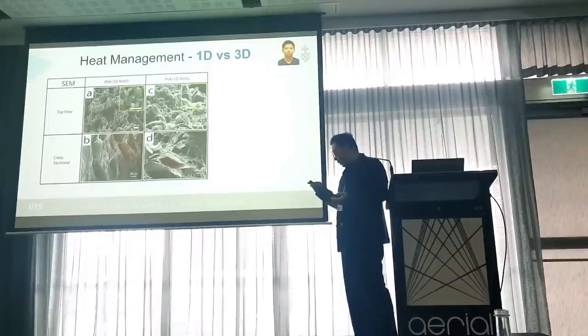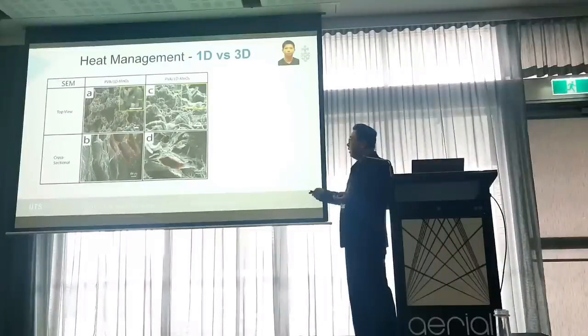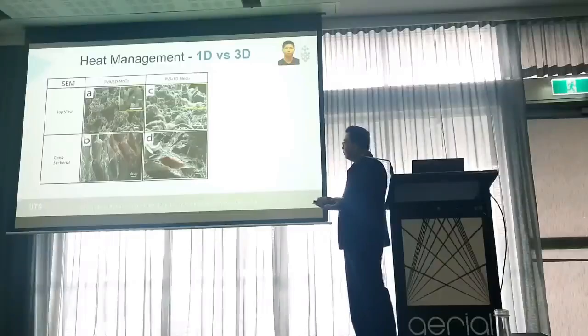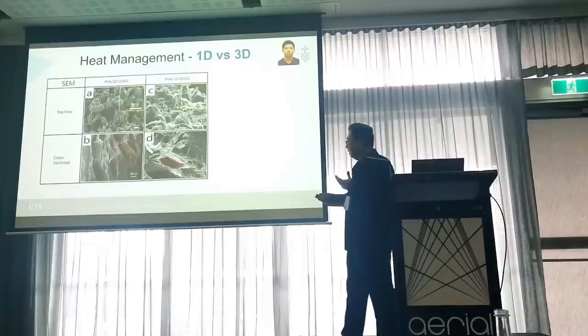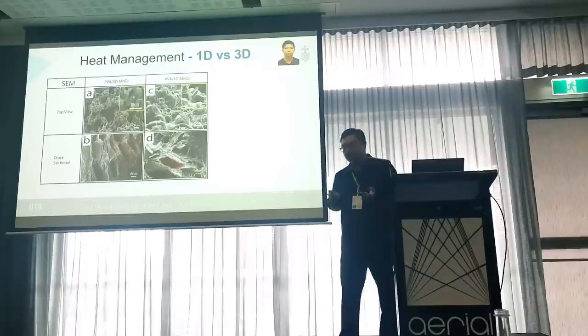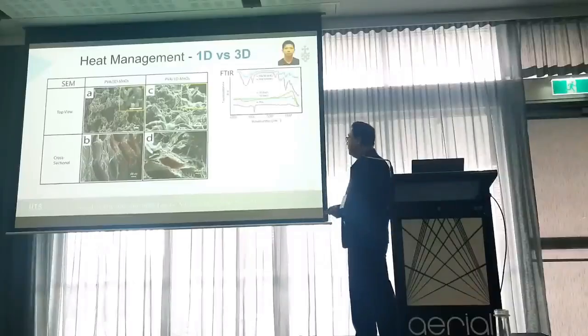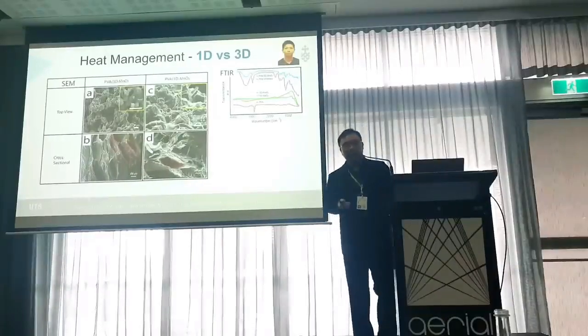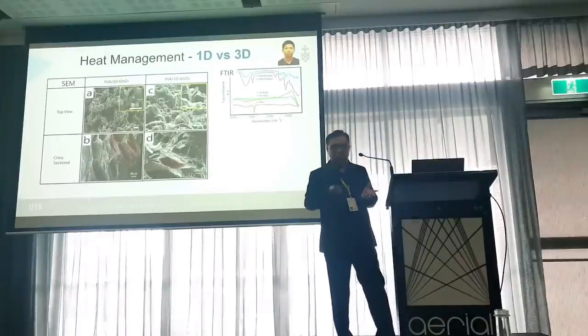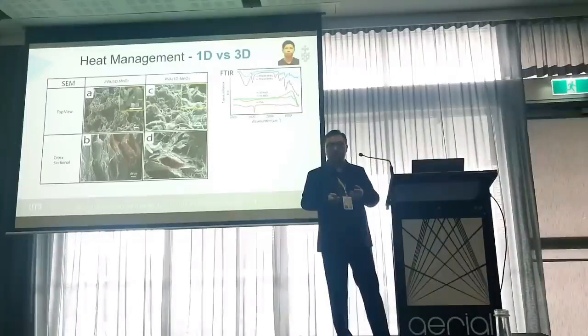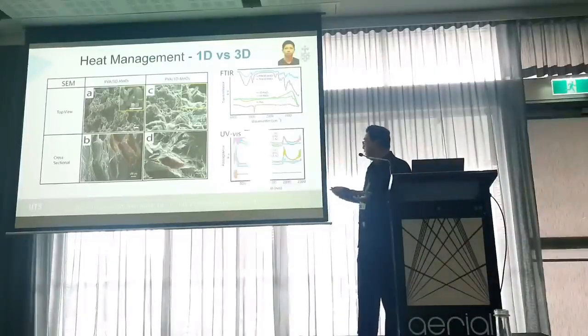Through the SEM image, we find that the 3D nanoparticles or 1D nanorods were embedded in the hydrogel matrix clearly. Both hydrogels have this microporous structure, and this structure will facilitate water transport within the hydrogel. We also characterized them by FTIR. As you can see, all the characteristic peaks were observed, as well as using the UV-vis.